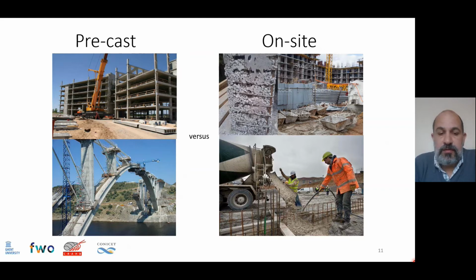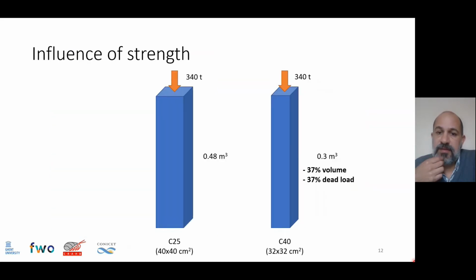can achieve lower levels of production of waste and more efficient use of the material, especially regarding the performance of the structures, which for precast is much higher in general terms than the construction on site. Of course, some types of works will always be made on site, but when we are talking about reinforced concrete, we observe significant defects in the construction on site that are generally more difficult to avoid than in the precast industry. So incrementing the proportion of the precast industry can certainly achieve more efficient rates in the use of cement and concrete. And a similar increase in efficiency can be achieved by increasing the strength class for concrete.